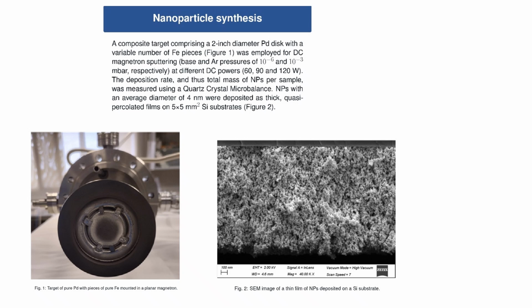To produce these nanoparticles, we use a composite target made from a 2-inch pure palladium disc with a variable number of iron pieces mounted on it, as in figure 1. The deposition was carried out by DC magnetron sputtering at a base pressure of 10 to the minus 6 millibar and an argon pressure of 10 to the minus 3 millibar. We test 3 different DC powers, 60, 90, and 120 watts, to control the iron amount in our nanoparticles. We measure the deposition rate, and thus the total nanoparticle mass per sample, using a quartz crystal microbalance. The resulting nanoparticles had an average diameter of about 4 nanometers and were deposited as thick quasi-percolated films on small silicon substrates of 5 by 5 millimeters.